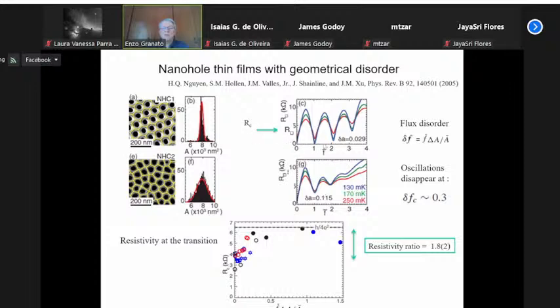Here, the resistivity is shown as a function of frustration. Just above the transition in the insulating phase, it oscillates as a function of frustration, as we'd expect, with minima at the integer values. There are no minima at 1/2, because, as we just explained, it's probably due to the fact that it's a honeycomb array of grains, so it's a triangle of holes. If you look as a function of temperature, there are 3 temperatures here. Each line in a different color means a different temperature. The red one is a higher temperature, the blue one a lower temperature. You see that if you change the temperature, the lines cross at a particular value.